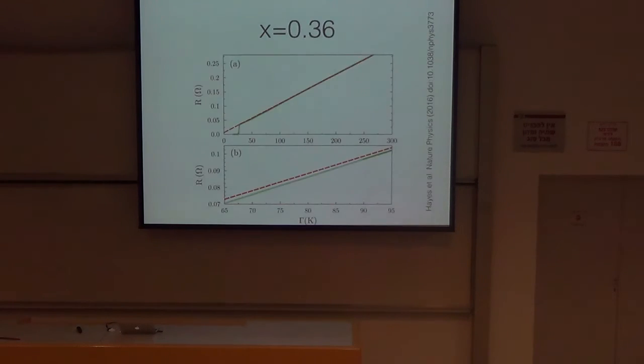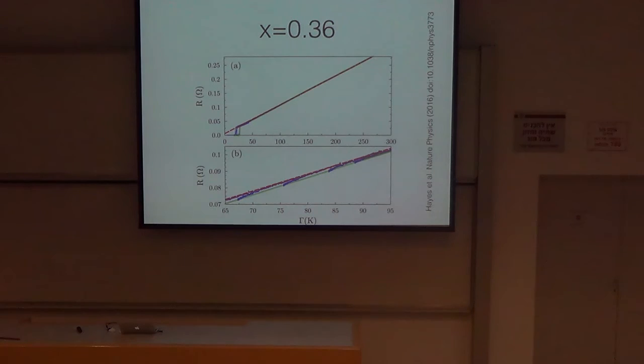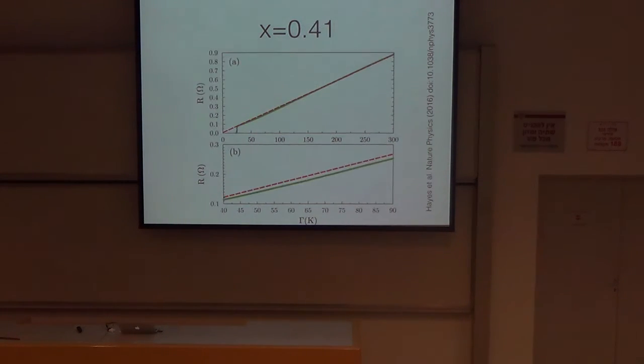Okay, so let's go to some other dopings. Here's one that's a little bit more overdoped. Again, apparently almost the same thing happens, maybe some deviations at very low temperatures, but certainly at these intermediate temperatures and fields, you get the same kind of asymptotic behavior approaching this T-linear line. Again, even more overdoped, similar kind of asymptotic behavior, but maybe because you're a little bit further away from the critical point, you never actually quite reach this line.